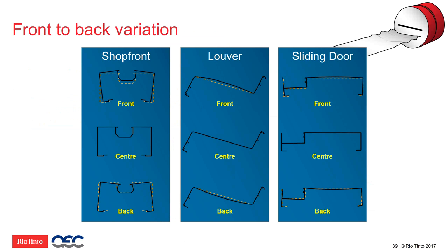Well, first, it's to really watch for profiles that are more than 80% of the circle size, okay? When profiles become too wide, then clearly you can introduce more variability as illustrated on this slide. Another aspect is to add a large baffling ring on the front of the die, about 2 inches, that also helps stabilize things. And billet taper heating, okay? So again, trying to have the front of the billet against the die hot and colder toward the dummy block can definitely help reduce this kind of variability.